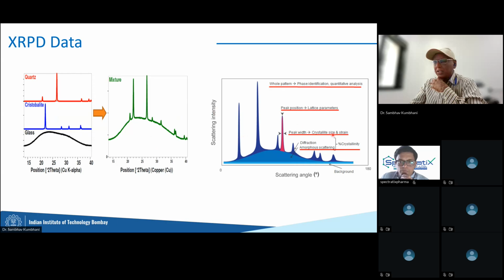In a typical XRD spectrum, the information that we get is all here. First, looking at the whole pattern, like I said, the entire pattern, we get what kind of phases might be present in it, and in how much concentration also we can find. So this is the first information we get in a typical XRD. Looking at the peak positions, at what 2 theta angle the peaks come up, tells you about the lattice planes of your crystals. How thick the peaks are, or the area under the peak, tells you the crystallite size, how big or how small the crystals are. Basically, the bigger the crystal, the sharper the peak. Okay.